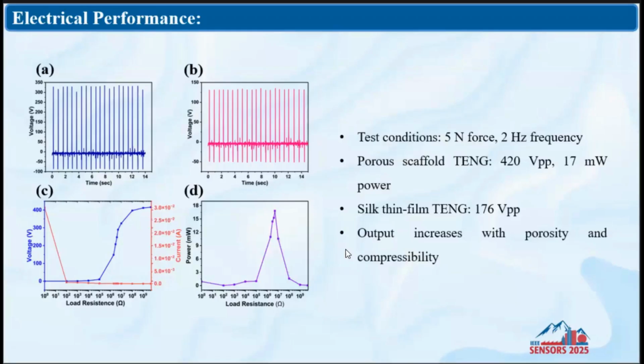And then, as you apply contact and separation, applying and releasing the mechanical force continuously, you will get this kind of graph, a continuous AC signal. Then we applied different load resistances, and based on the resistance, we looked at how the voltage varies with respect to the current. As you can see, when you apply the load resistance, the voltage increased and then the current decreased due to the internal resistance of the TENG device.